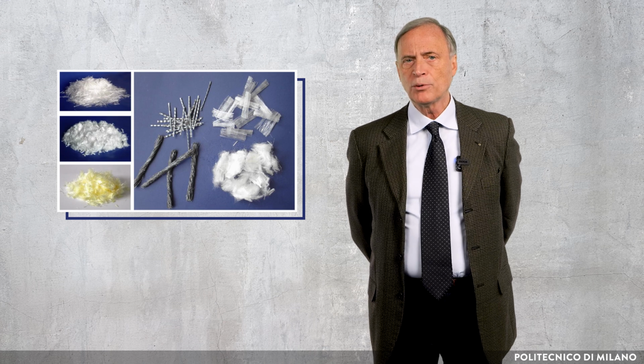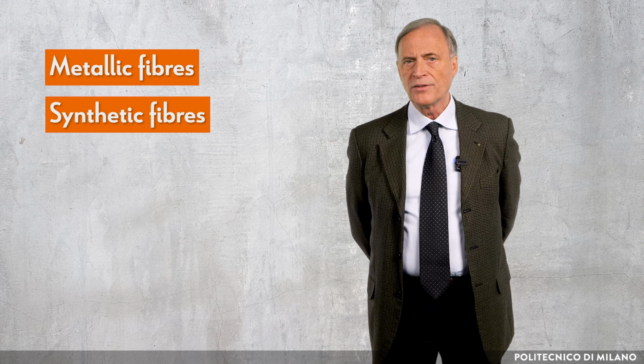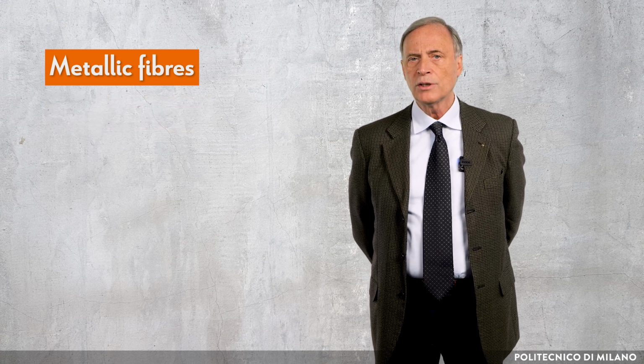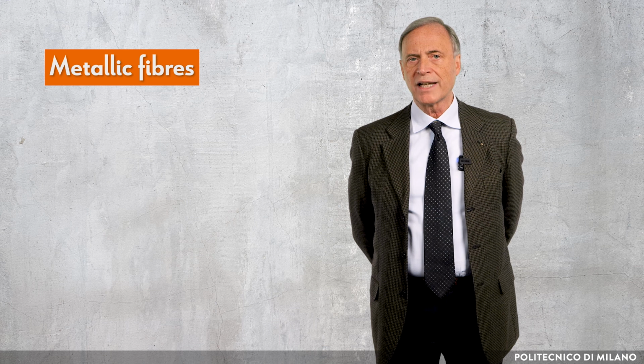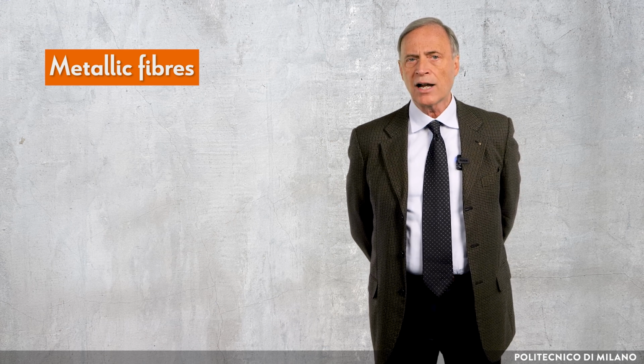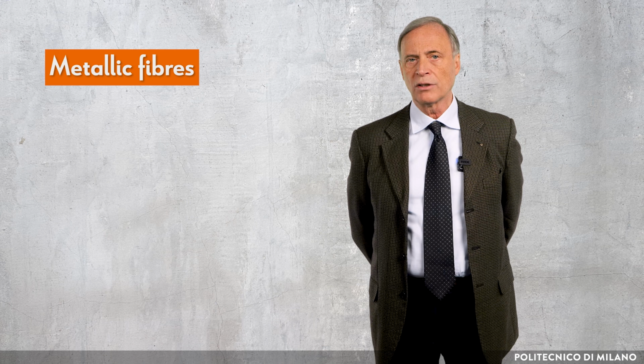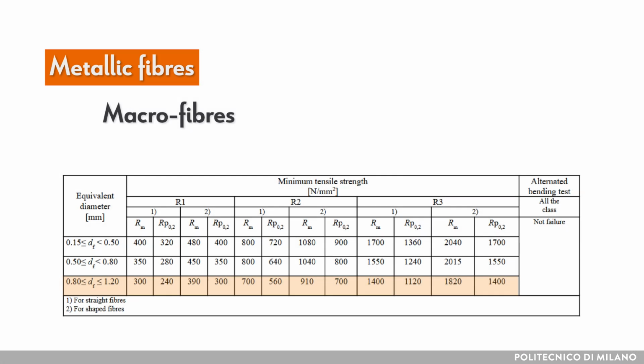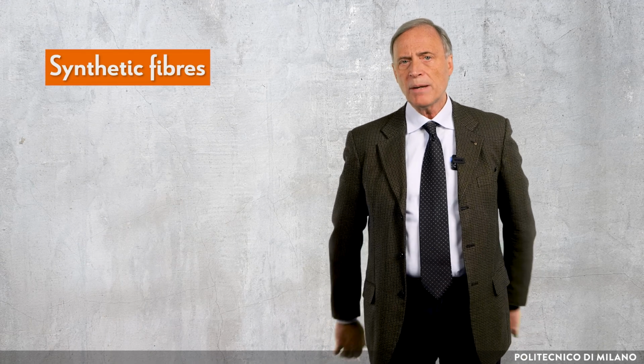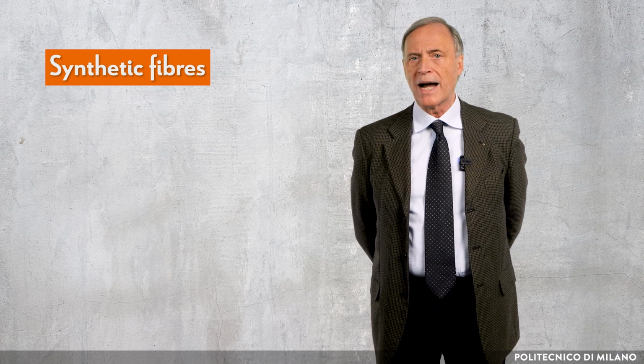In the market, many types of fiber are available. It is possible to split the fiber world in two large categories, the metallic and the synthetic fibers. The former are the most used until now to guarantee high performance of fiber-reinforced concrete and can be split into three classes according to the equivalent diameter of their cross-section: macrofibers, with a diameter in the range of 0.8 to 1.2 mm, mesofibers in the range of 0.5–0.8 mm, and microfibers in the range of 0.15–0.5 mm. It is worth noting that synthetic fibers can reach a minimum diameter in the order of 10 microns.